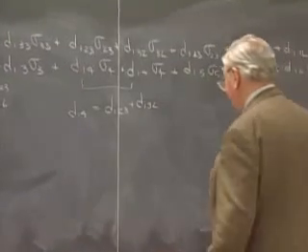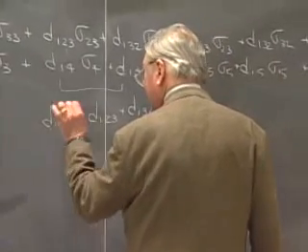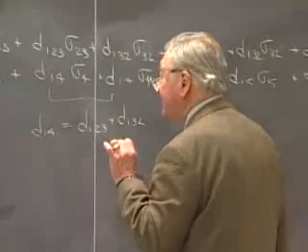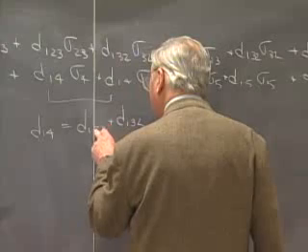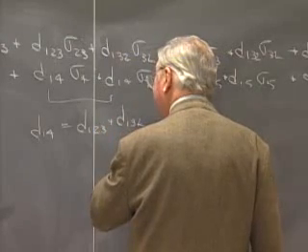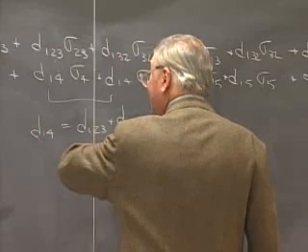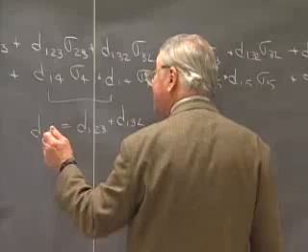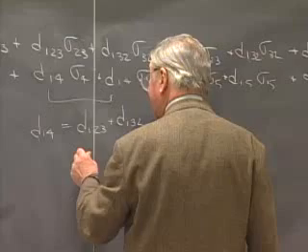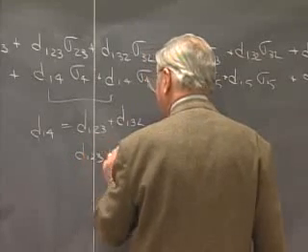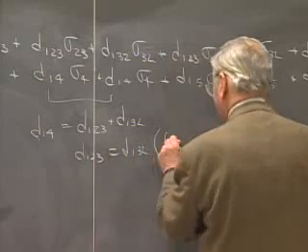And then we saw last time in our earlier meeting, from the converse piezoelectric effect, which expresses strain in terms of an applied field, where the elements of strain 1,2,3 and 3,2 appear in separate equations, and knowing that the same array of piezoelectric coefficients amazingly describes the converse piezoelectric effect as well as the direct piezoelectric effect, we know that D123 equals D132, and that is from the converse effect.